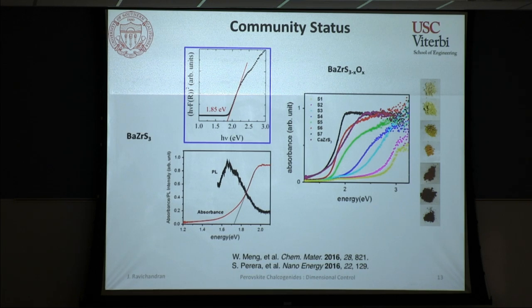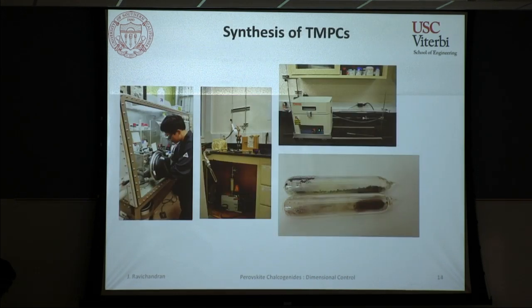So we decided to go about doing this, and we knew that just taking elemental sulfides and powders and mixing them and cooking them for a long time is not going to solve the problem. So we went about taking these powders. We also added a little bit of halogen. So the insight was to take halogen and let it react with highly refractory, high melting point materials like zirconium, and that allows us to lower the melting point of this system, and hence the reactivity is a little bit better.